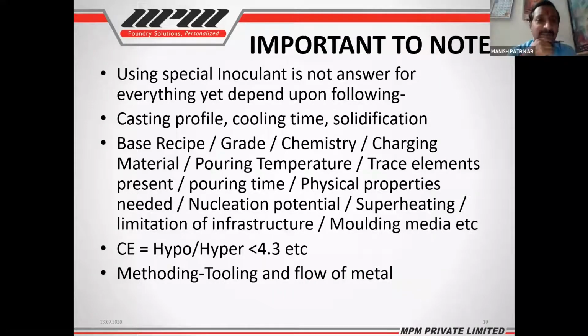So coming to the inoculation topic, I urge all foundrymen, whenever they look at inoculation or inoculant as something which will do magic, please remove this from your mind, because using special inoculants like cerium, bismuth, strontium, or zirconium is not the answer for any of your issues. It is the last solution. As DG has already said in his presentation earlier: casting profile, cooling time, solidification, basic recipe, grade, chemistry, charging material, pouring temperature, trace elements, nucleation potential, superheating, limitations of infrastructure, molding media, hypereutectic combination, everything, methoding, tooling, and flow of metal.